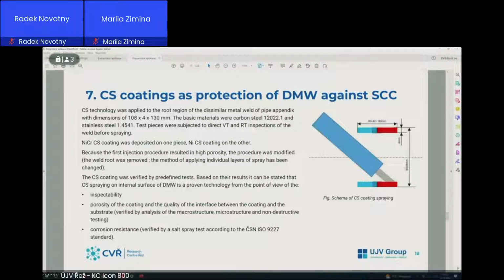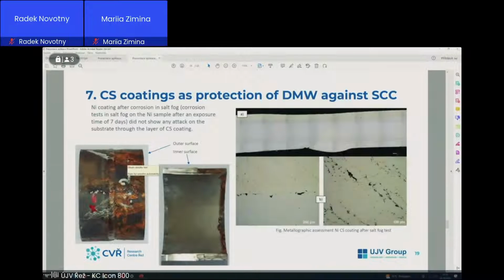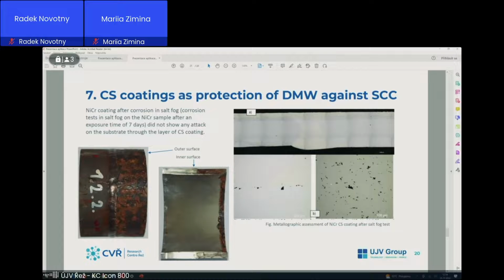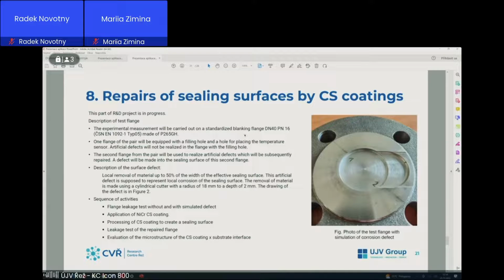And the results are here. Yes, there is some porosity as concerns nickel powder, but samples survived tests in salt fog, and we didn't see any attack on the substrate through the layer of cold spray coating. As concerns porosity, nickel chrome is better than nickel powder, and the results again were very good after tests in salt fog. And the last example will be done in November and December this year.